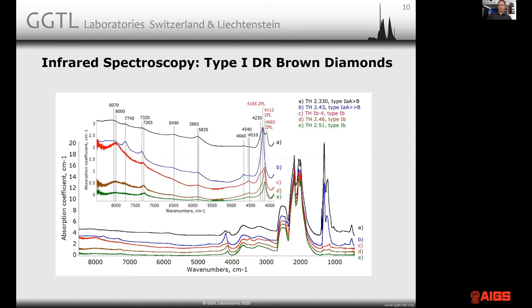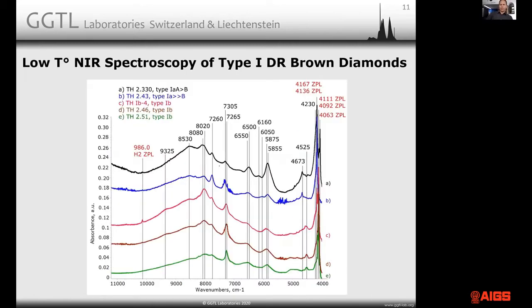So it's clearly and directly linked to the vacancy clusters, but also to nitrogen, since we have it only in nitrogen-containing diamonds. Type 2 diamonds don't contain them. Now, using our near-infrared spectrometer, we recorded all the amber center absorptions of those diamonds that you've seen just before at low temperature. And low temperature spectroscopy basically, first of all, proves that these are actually electronic transitions and not vibrational centers, as the many defects in the infrared are.